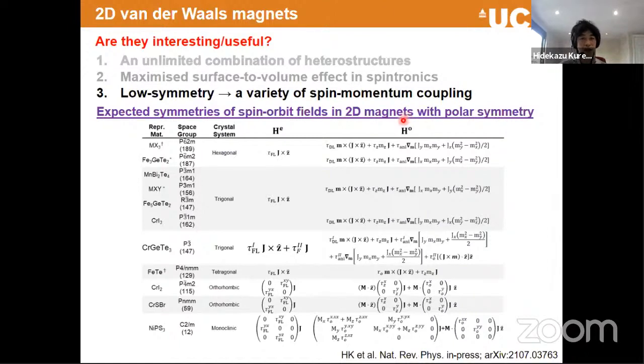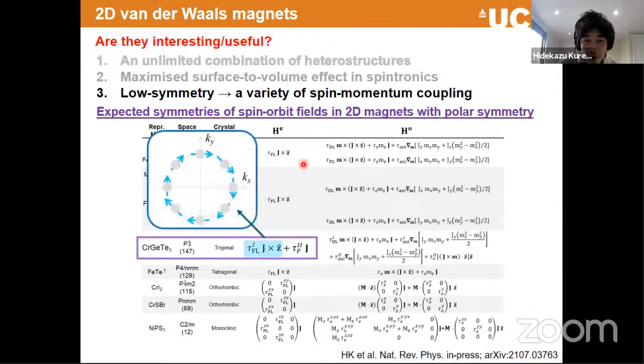So by doing so, we can make lots of different spin-orbit torques from the bulk symmetry or interface symmetry. I just pick a particular material. This is chromium germanium telluride, and this is the effective field when you apply the current. Normally, because of the polar symmetry we add, we create some kind of chiral spin texture. I just show you one subband of this. That can create an effective magnetic field when you apply the current, and this field direction is perpendicular to the current in plane.